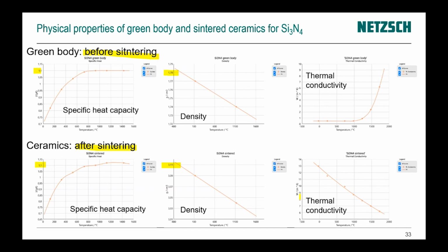And the next one is thermal conductivity. Here the change in thermal conductivity is really very high, because at the beginning we have a green body as a porous material or just a mixture with the polymer. After sintering, we have a material which is almost solid with crystals or glasses inside, and then the thermal conductivity of the final product is much higher than that of the original product. For example, for silicon nitride, the thermal conductivity of the original material before sintering at room temperature is 0.5, and for the final product after sintering it is 13 watts per meter Kelvin. So it is almost a factor of 25. It is a really very, very big difference in thermal conductivity.